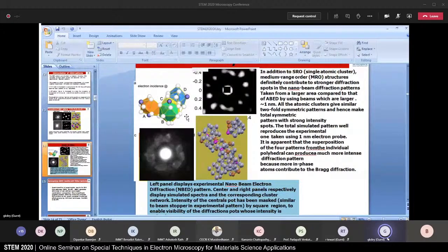So you allow the 2 clusters to be diffracted together, and you get a diffraction pattern which is a little complicated here. The simulated pattern is here for a structure like this, and after filtering this, we could see a match between these two, and therefore it was possible to say that this is how the two clusters are joined.